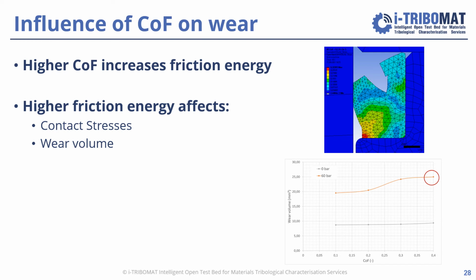And you see here in this graph that was produced with a constant Archard wear coefficient, that although for zero chamber pressure there is basically a baseline with constant wear volume, for higher chamber pressure this influence becomes highly pronounced, and the wear volume increases a lot if you increase the coefficient of friction.